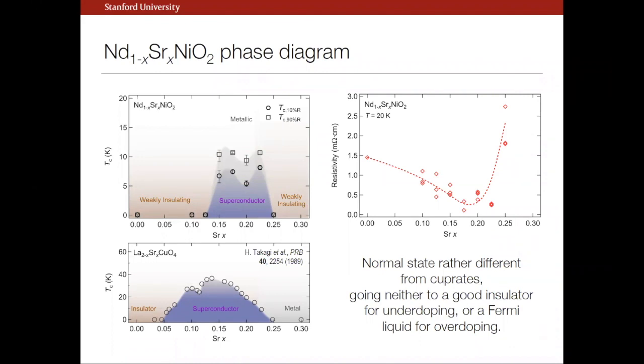And this is for all the samples, and you can see that despite the scatter, the overall trend is very clear. That the superconducting dome is associated with a minimum of resistivity, and at a very hand-wavy level, this would be kind of a border of the Ioffe-Regel limit, right around here. But what's quite different from the cuprate is we neither go to a good insulator on this side or a good metal on that side. And maybe I should stop, but happy to discuss that a little bit more.